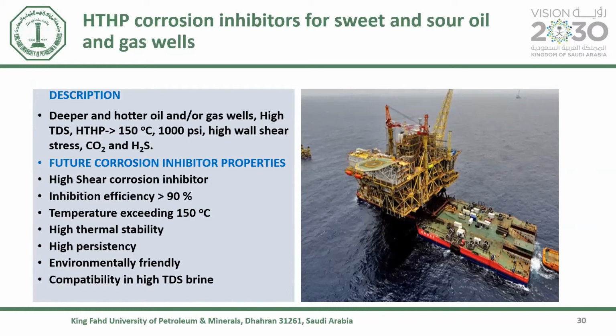So these are some of the challenges that I have outlined here, because we know deeper and deeper water wells available, they have very high TDS, high temperature, high pressure condition, high wall shear stress, CO2 and H2S. So how can we develop corrosion inhibitors that can meet this requirement? High shear corrosion inhibitor, high efficiency, exceeding more than 150 degrees Celsius, and high thermal stability, high persistency, especially for batch application, and also meeting environmental requirements, and compatibility with high TDS brine. So this is a huge challenge.